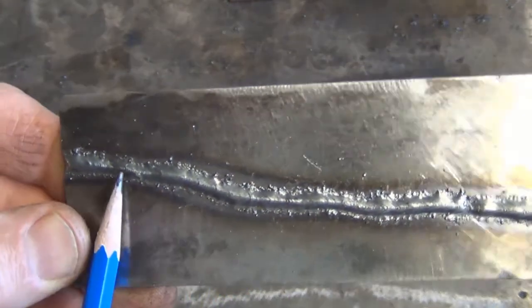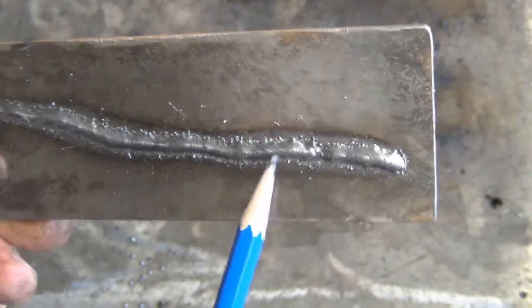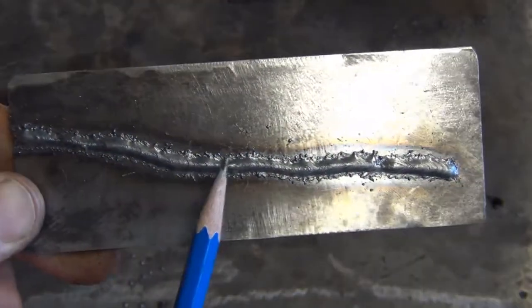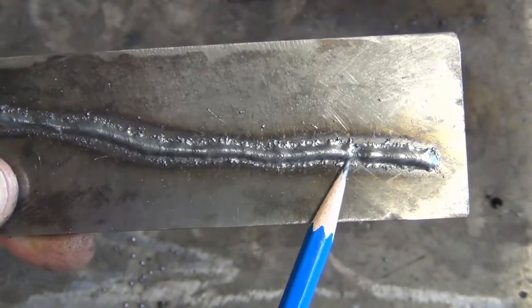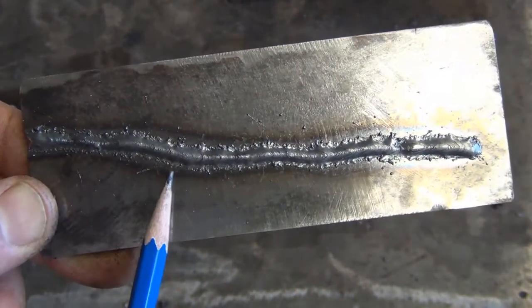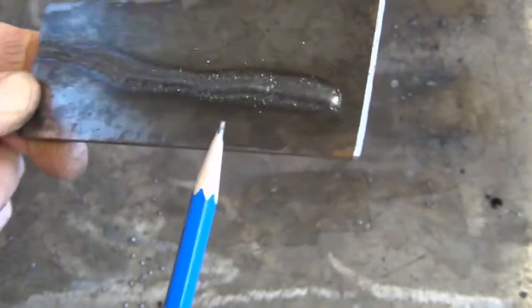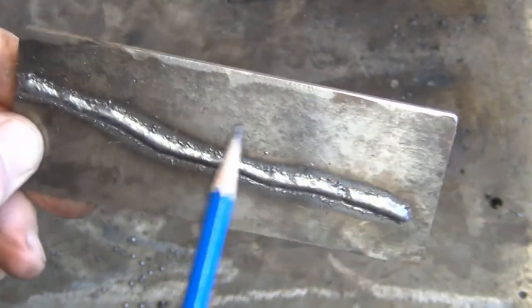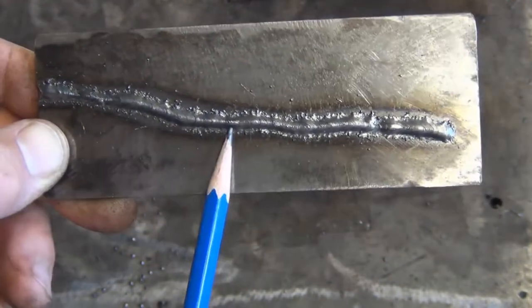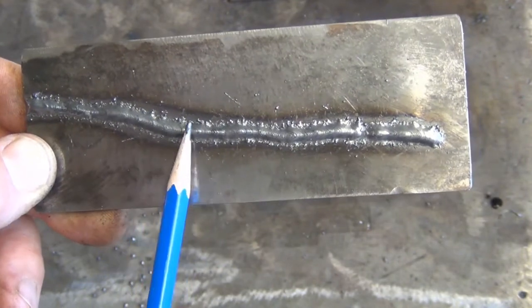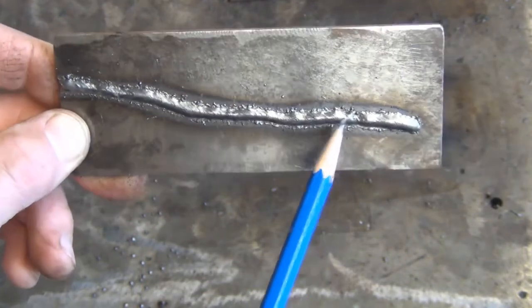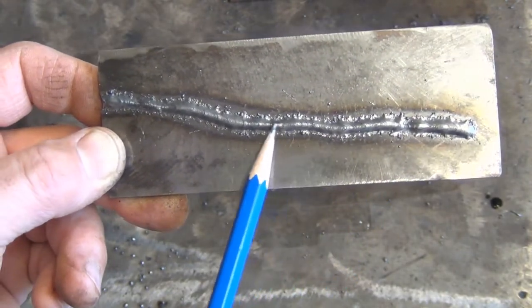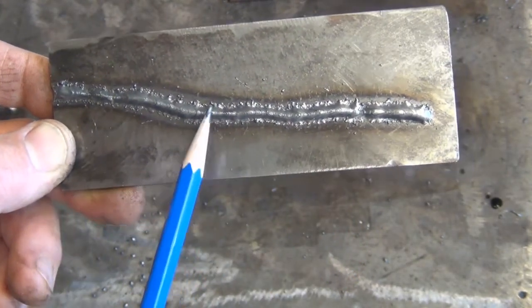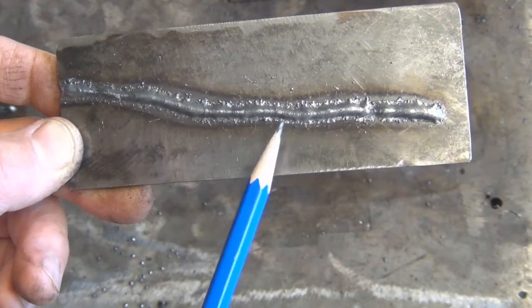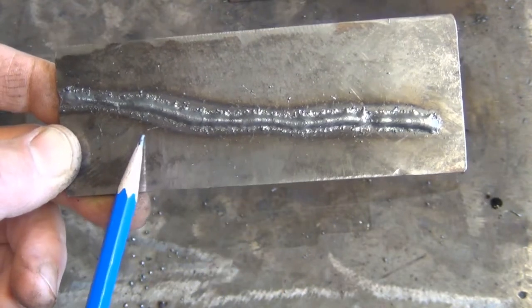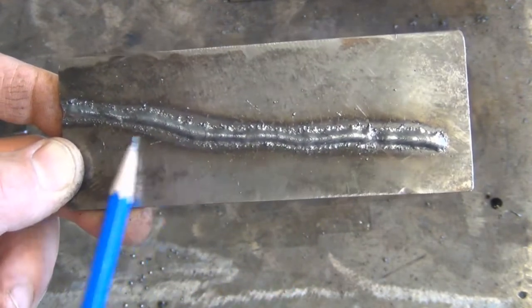This one is thin and ropey, like our last one. But if you look carefully, you can see quite a bit of spatter all along the side of the weld. Okay, it's thin, it's ropey. What that tells me is that the amperage and wire speed may in fact have been correct. However, the welder has traversed way too fast. Way too fast. So what I would do with this one is I would try slowing my feed rate and see what happens then. That's all it's going to take in this particular sample.